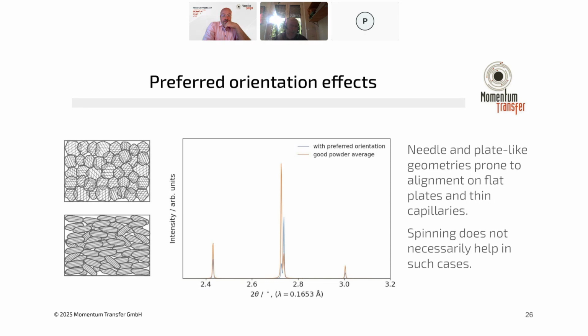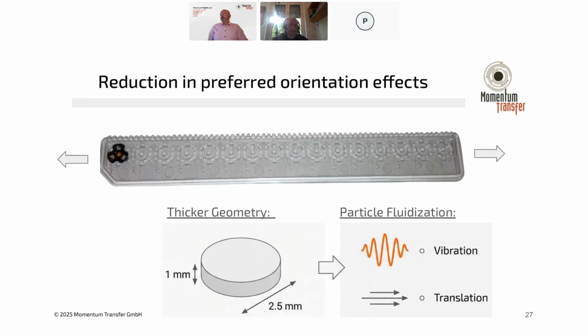So with Bragg-Brentano or Debye-Scherrer geometries, you can exacerbate this alignment effect because, for instance, if you have a flat sample holder and you're putting your powder down onto the sample, they tend to align along this flat plate. And similarly, if you have very thin capillaries and needle-like morphologies, for instance, then the needles tend to align along the capillary. And spinning your capillary or spinning your plate doesn't really improve the data in these cases, because as you spin it, you're still sampling the particles from the same direction. In our case, we use a slightly different flat plate transmission geometry, and we have these sample holders with wells that are cylindrical, about 1 millimeter in thickness and 2.5 millimeters in diameter.